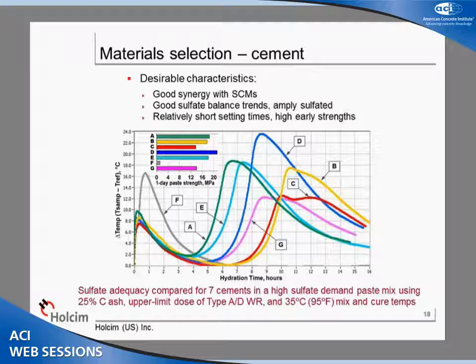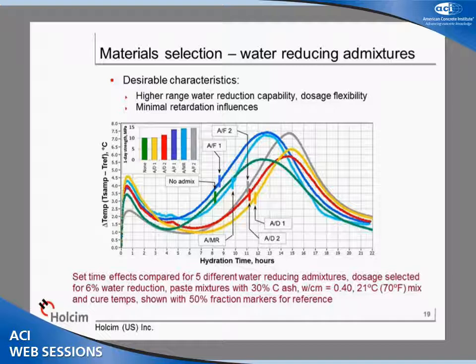Here 7 different cements are compared in an otherwise identical mixture. And you see the difference in the onset of hydration that results in different setting times for that combination. And in one case, we actually have a cement that completely failed the test and produced essentially no measurable one-day strength. So if you have different cements to choose from, it might behoove you to pick sample A or sample E as the faster setting cements in this combination of materials that you might be dealing with. Just an example. You could certainly do the same thing for your chemical admixtures.